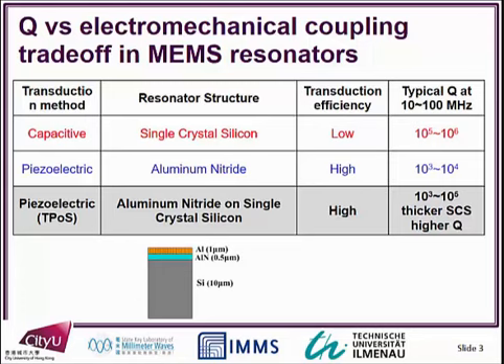thousands or so. And what's been pioneered by Farouk is this thin film piezoelectric on silicon, whereby you combine the goodness of silicon together with the aluminum nitride. You get low damping from the silicon, you get nice transduction efficiency from the piezoelectric, so you get the best of both worlds, and you get slightly higher quality factors. You can reach up to about 100,000, depending on the thickness of silicon. So that's what a thin film piezoelectric on silicon stack looks like. You've got aluminum nitride, sandwiched between an electrode and silicon at the bottom.